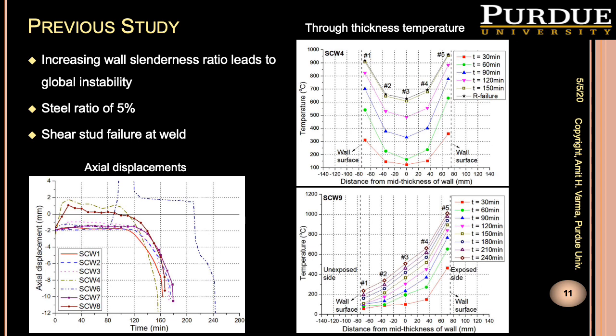We found from their test data that increasing wall slenderness ratio leads to global instability. And that's when the wall slenderness ratio becomes very large. They had that happen for just one specimen. Generally, they found some shear stud failures at weld locations, but this may be associated with how the shear studs were welded in their specimen designs. And the steel ratio was about 5% in their studies. Overall, this test data provides us with good experimental results to compare with, to benchmark the numerical models and compare with the results from the numerical analysis.